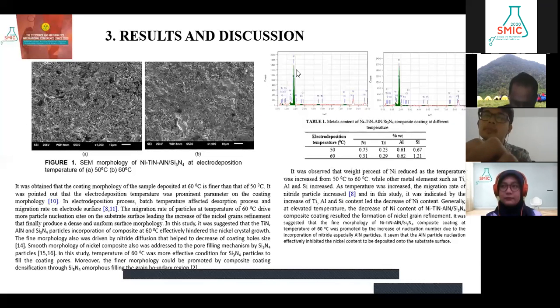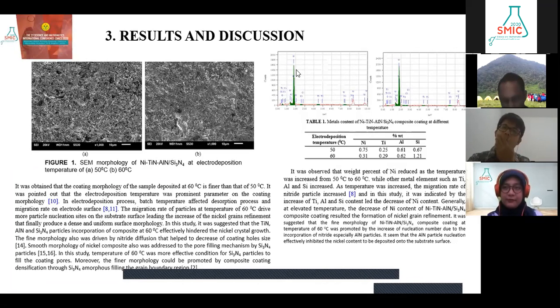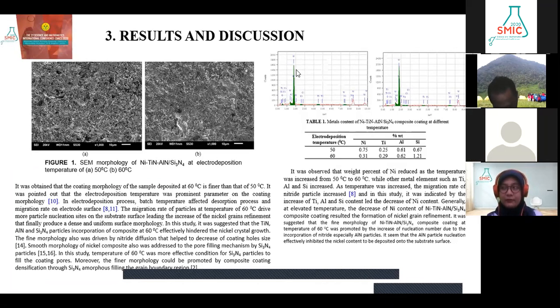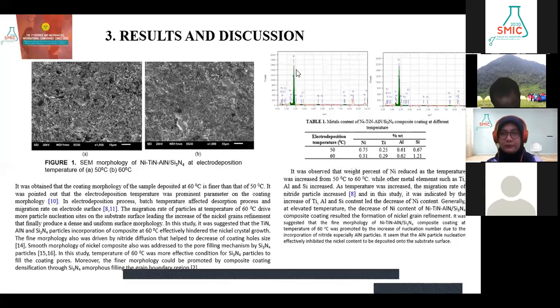From the result, it showed the coating morphology of the sample deposited at 60 degrees Celsius is finer than that at 50 degrees Celsius. It indicated that the temperature was a significant parameter on the coating morphology. In this study, it was suggested that nitride particles such as titanium nitride, aluminum nitride, and silicon nitride particles were incorporated into the composite at 60 degrees Celsius, effectively hindering the nickel crystal growth.